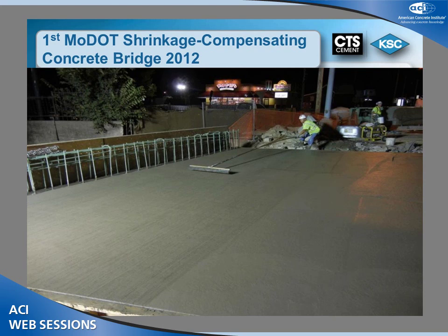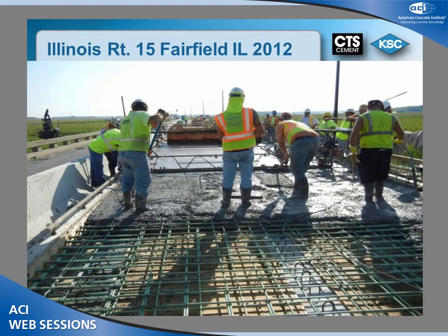It was very creamy, very easy to place. We were basically averaging 6-inch slump. We were running at around 5% air entrainment on the mix design. This was placed at nighttime. A very heavy trafficked area. The name of the road in St. Louis is Highway 100. Very heavy traffic area on the west side of St. Louis. Now, in Illinois, we did a bridge deck.